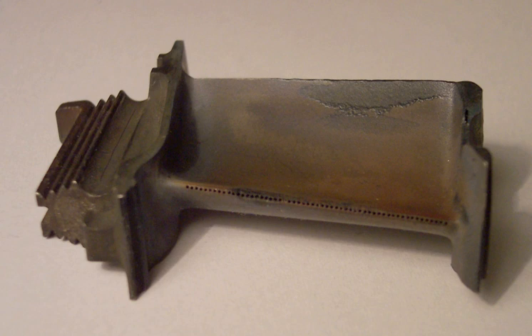The electron beam directed vapor deposition (EB-DVD) process used to apply the TBC to turbine airfoils produces a columnar microstructure with several levels of porosity. The porosity between the columns is critical to providing strain tolerance via a very low in-plane modulus, as it would otherwise spall on thermal cycling due to thermal expansion mismatch with the superalloy substrate. The porosity within the columns reduces the thermal conductivity of the coating.